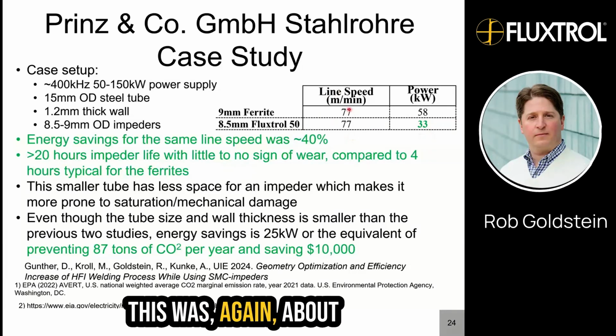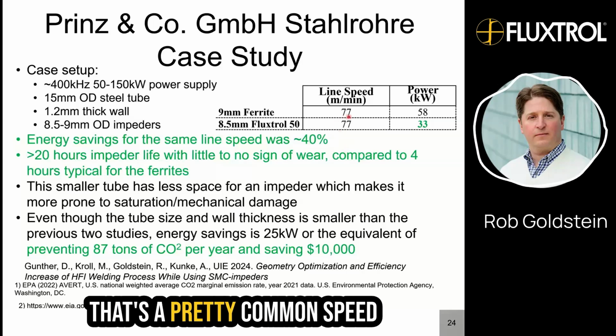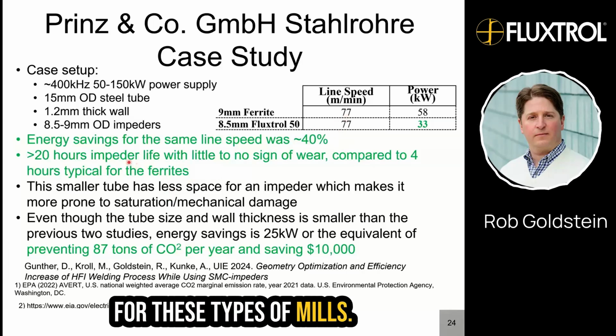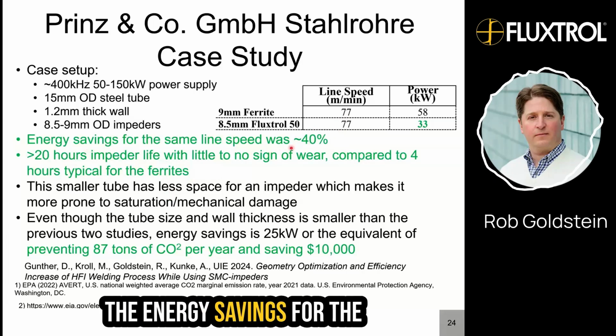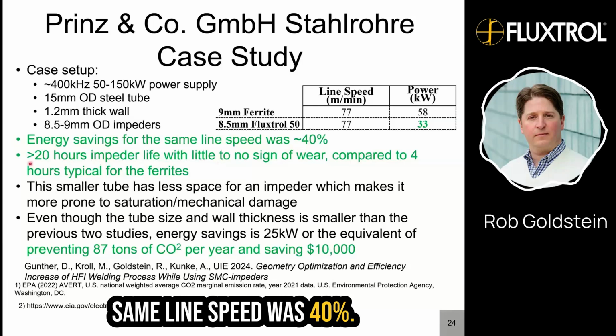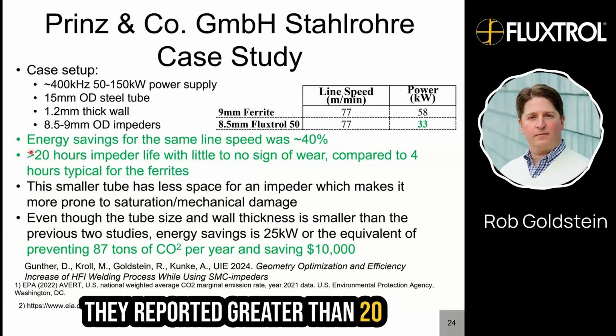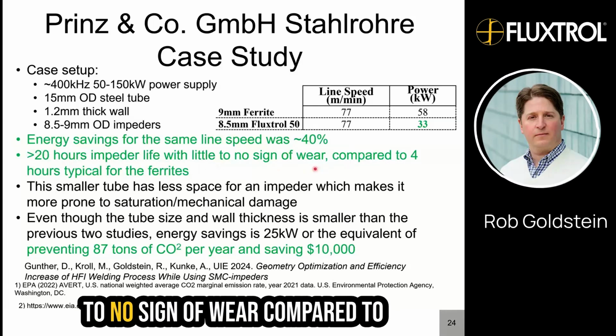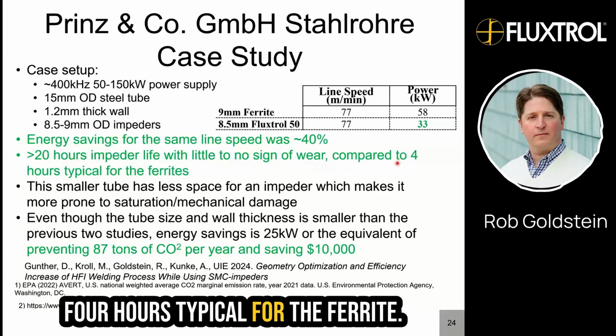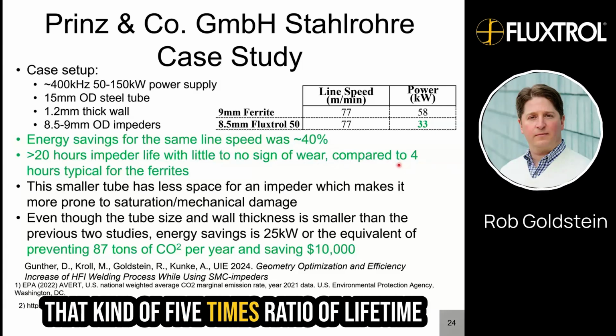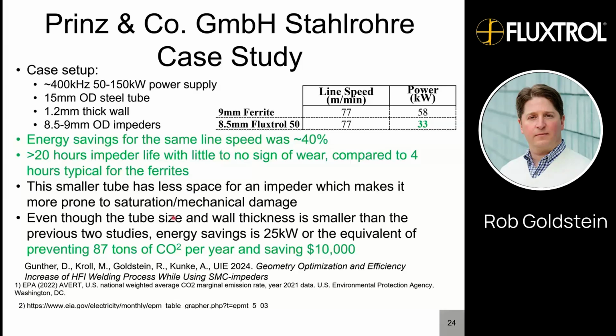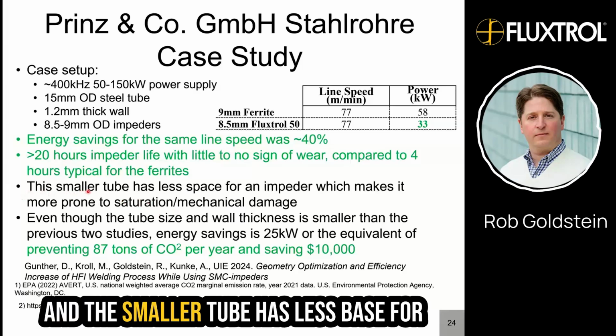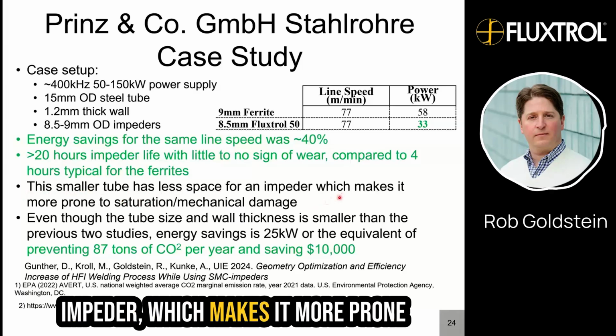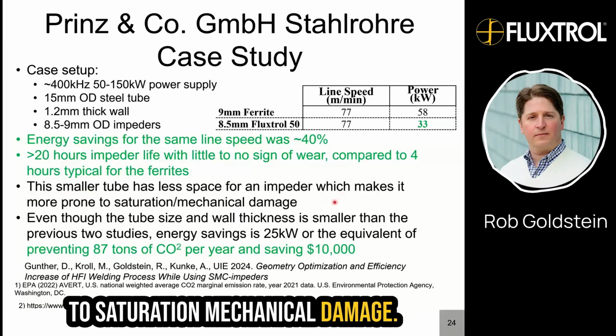This was, again, about 80 meters a minute. That's a pretty common speed for these types of mills. The energy savings for the same line speed was 40%. They reported greater than 20 hours of impeder life with little to no sign of wear, compared to 4 hours typical for the ferrite. That's about a 5 times ratio of lifetime. And the smaller tube has less space for impeder, which makes it more prone to saturation mechanical damage.